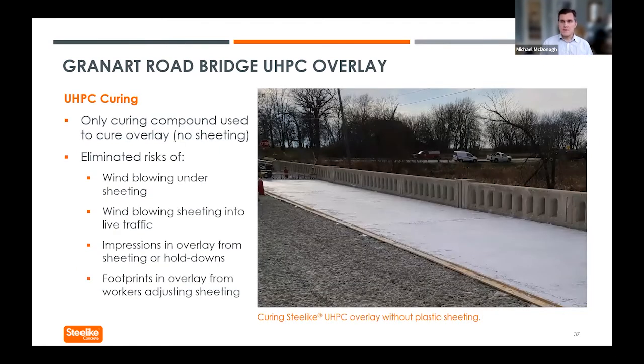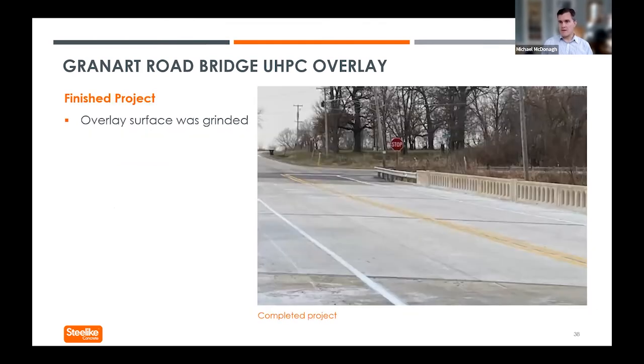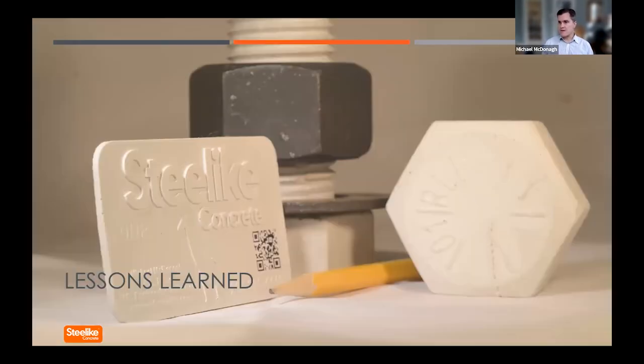Furthermore, Steelike UHPC can be cured using only curing compound. Its unique behavior allows it to restrict water loss by itself only with the help of curing compound. So sheeting is not needed, eliminating all the risks of it, which I identified previously. And then just to show the completion of the job, as with all UHPC overlays, the final surface was ground to provide skid resistance.